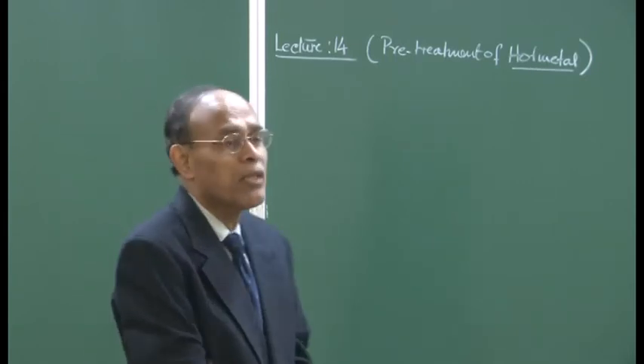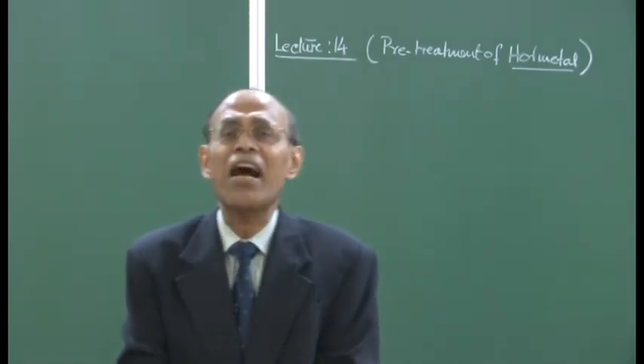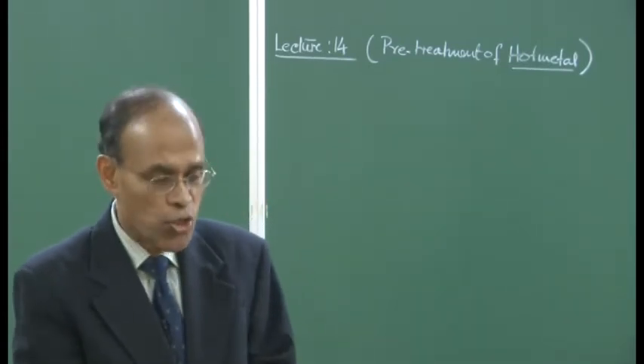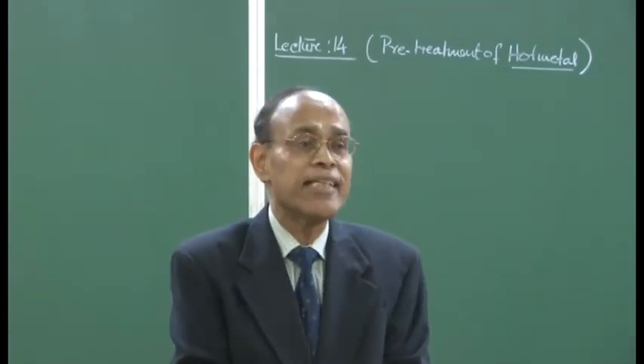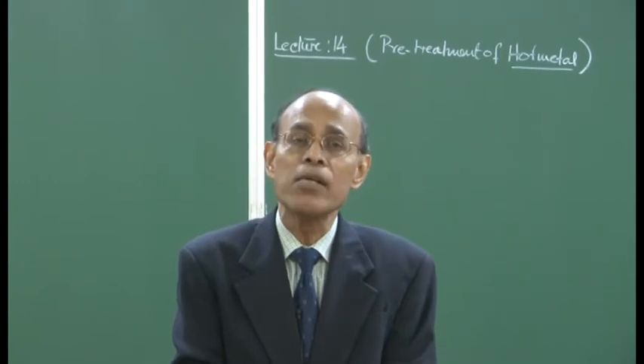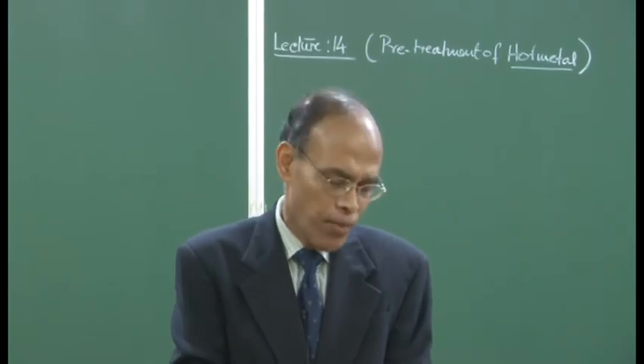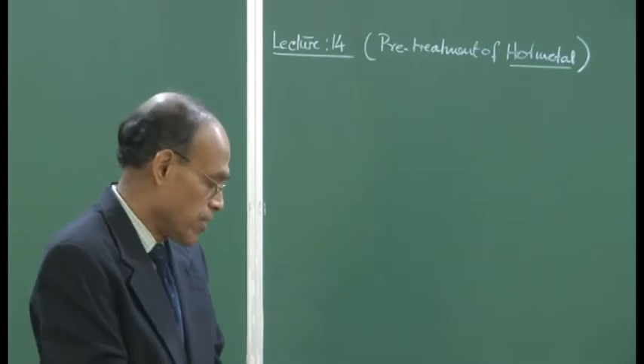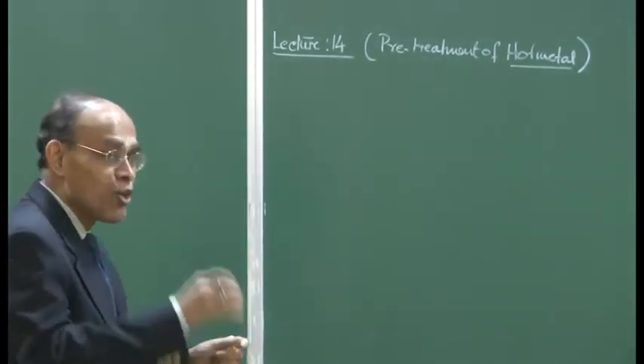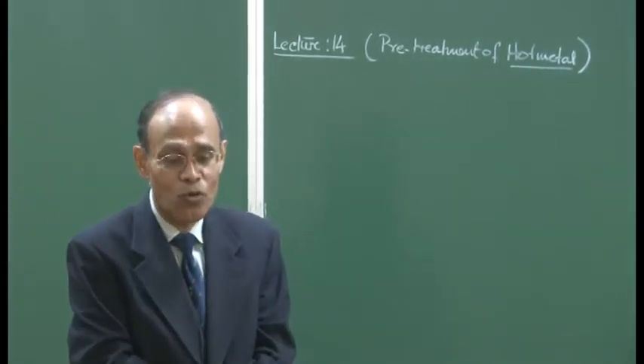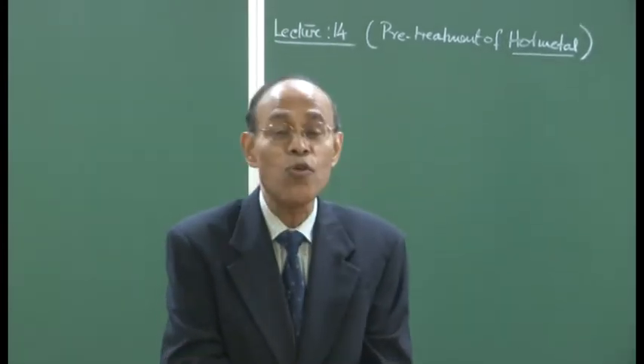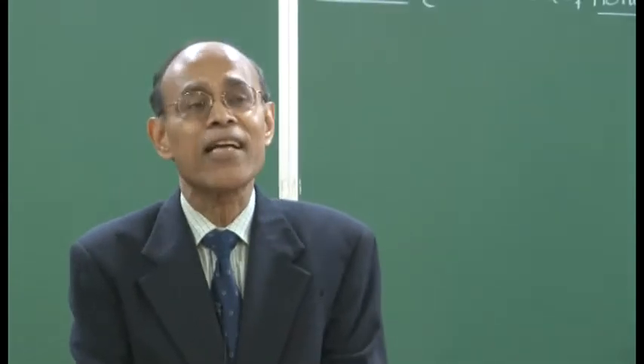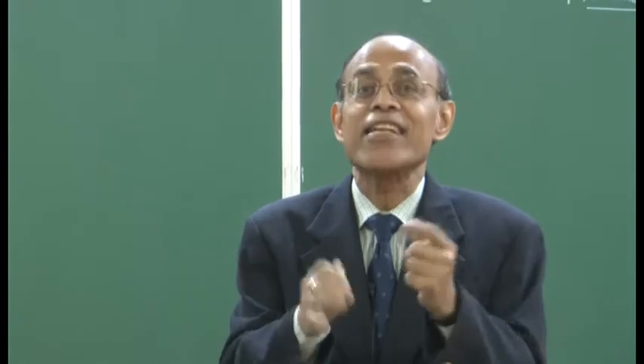metal. For example, if we use a very high hearth temperature, or in the bosh region, if the temperature is exceedingly high, in that case there is a chance that we may produce hot metal which will be extremely high in silicon content. And then you have to remove this silicon, and as you all know from your basic chemistry course, steel making becomes autogenous because of the simple fact that carbon oxidation as well as silicon oxidation during steel making provides the necessary heat. These are extremely exothermic reactions.